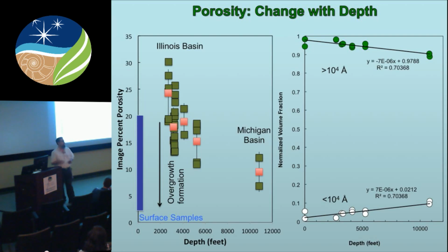The first is, and I'm going to mention this briefly in a little bit, as you get fluids into smaller pores, the properties of those fluids change because of the interaction of the fluid with the material that makes up the grain boundaries. So it's been suggested, and this was by J. Ag and Simon Emanuel, that because of that, the solubility of, say, quartz is larger in water in a confined pore than it is in a larger pore, and so it is less likely to precipitate there. That's actually the opposite of what's been suggested by an Ising model by Hedges and Whittle.